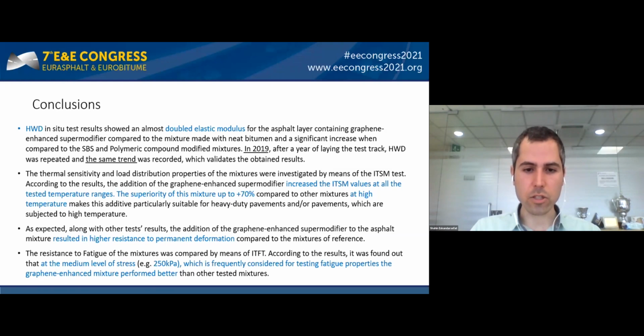The mixtures showed significantly better results when compared to the neat bitumen mixture, considering 250 kilopascal as a common medium level of stress for fatigue investigations. The mixture containing super modifier showed 60% better results, and significantly better results compared to the other plastomeric mixture.